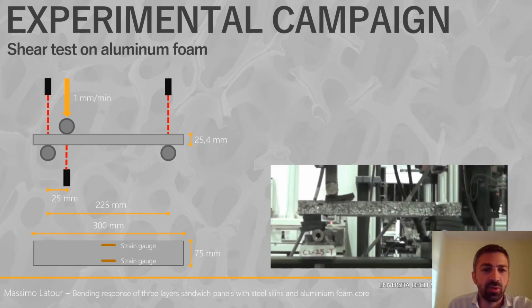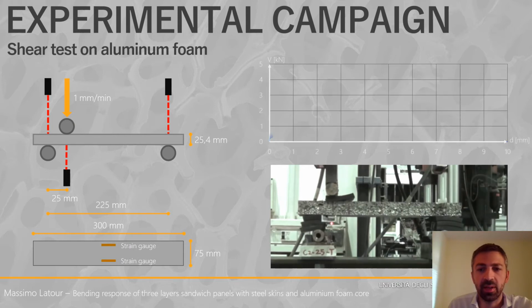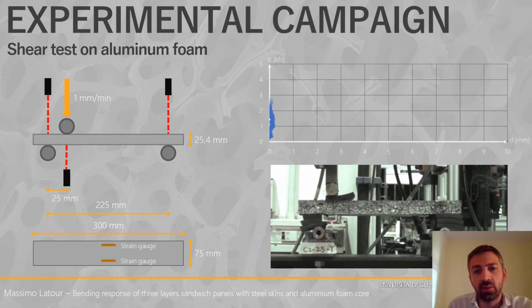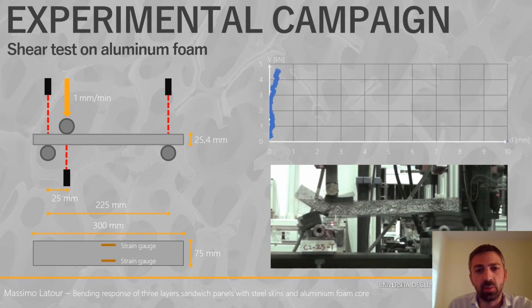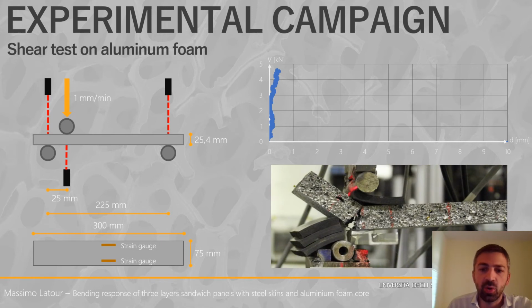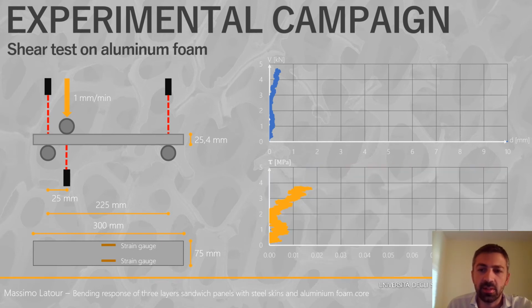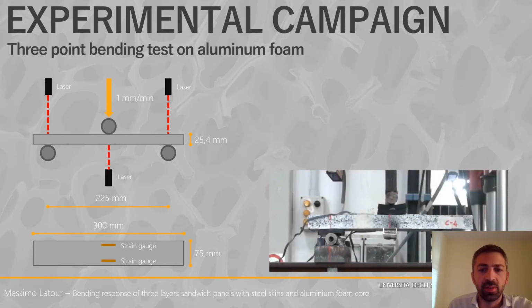Shear tests were also executed. The layout is very simple. The point of application of the load was very close to the support to promote the shear failure of the panel. This is one of the typical tests that we have executed. These tests were showing a resistance of the aluminum foam in shear of about 4 megapascal. During the test we monitored also the deformations, and this was done also in the 3-point bending tests, which are shown in the slide here presented.